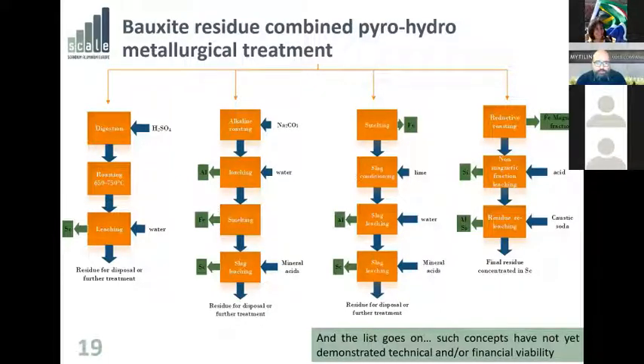So by using sodium carbonate, you can solubilize the phases that contain alumina in the bauxite residue to a point that you can recover them with simple water leaching. And then you have a residue, which is now free of alumina and soda and some silica. You do a smelting, you take out the iron, and then you leach eventually the slag to recover scandium and other elements.